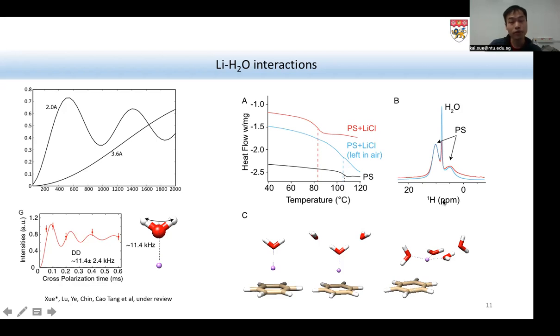We found this in our system by measuring proton 1D. In here, the red one is the measurement before we leave the sample in air for some time, and in blue is the proton 1D that we measured once we left the sample in air for some time. We measured these two states of the same sample, just before and after exposure to air. When it's not exposed to air, we observe a big transition of glass transition temperatures. After we leave it in air for some time, it actually moves back. So this would be an indication that the interaction is actually quenched.